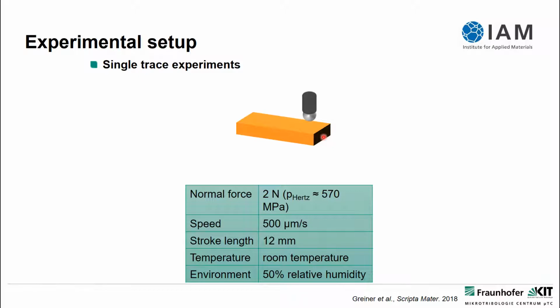So we have a sapphire sphere which is in contact with high purity copper. It's an unlubricated contact, and we control the environment it is in. What I will show you today is all in 50% relative humidity air at room temperature, and we do a really mild tribological load.